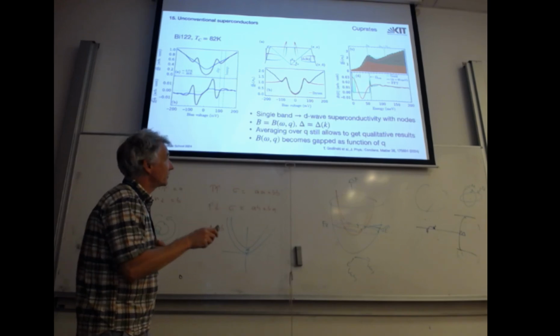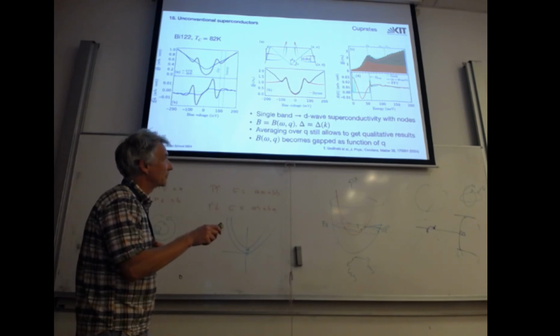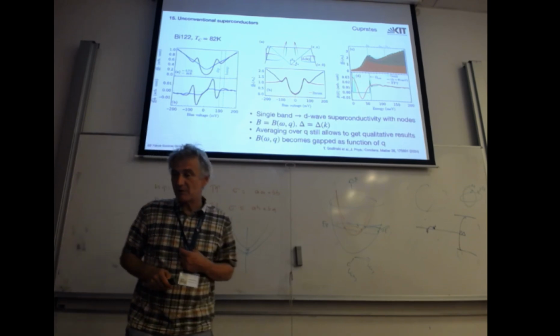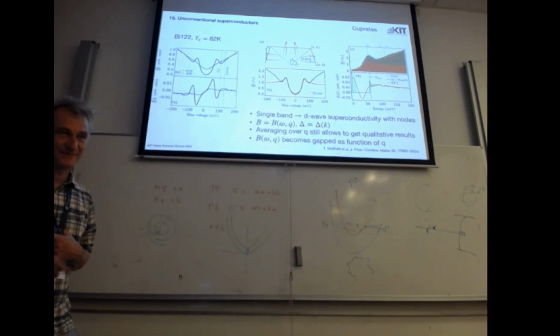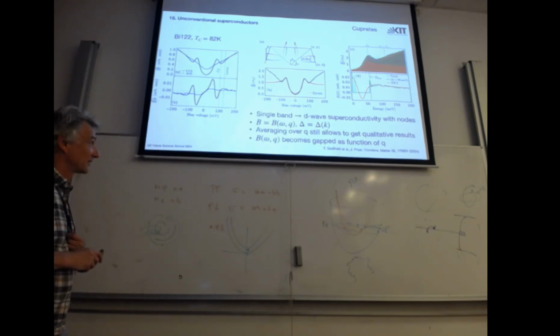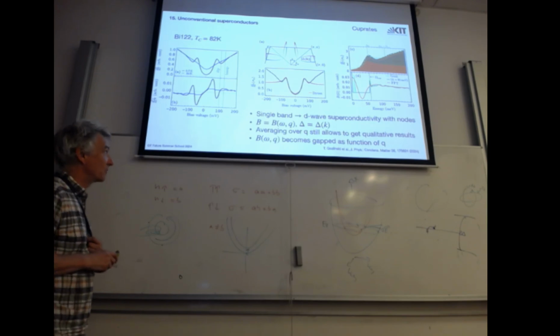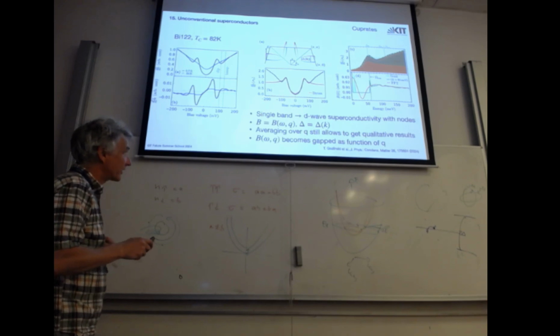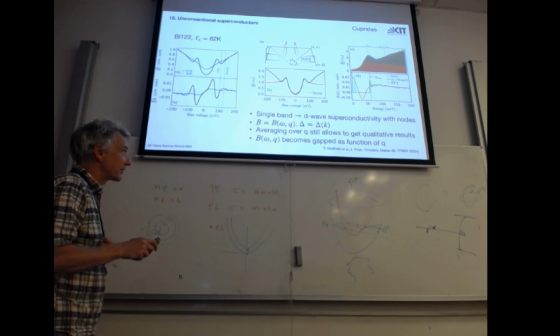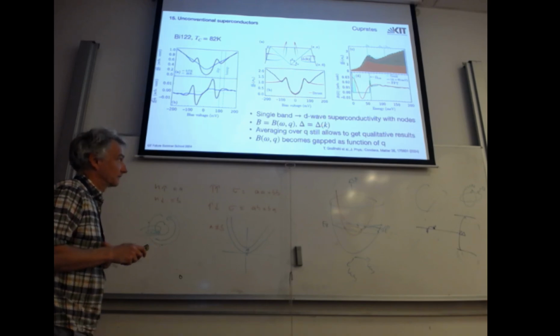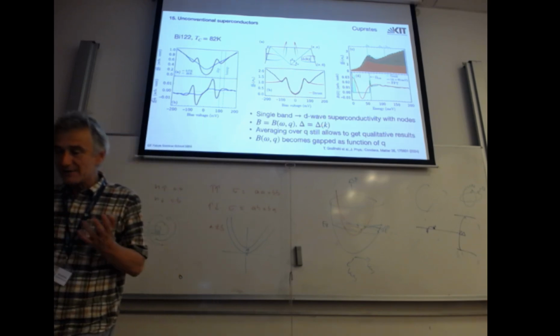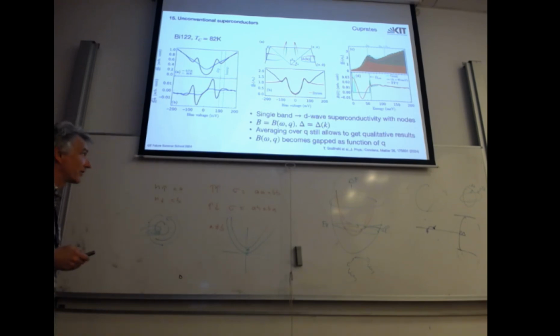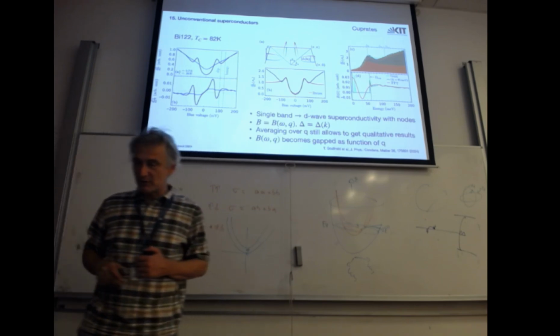Same argument, deconvolution, and again, what we see is a gap, a peak, a continuum spectrum. So maybe this is also magnon mediated. This is an assumption. Our theory cannot do better. So our bosonic function is not anymore only a function of the energy, but also of Q. And actually delta becomes a function of K. Our STM measures without resolution for K, so we have to solve everything for every K and add up everything, so the agreement will not be so nice.